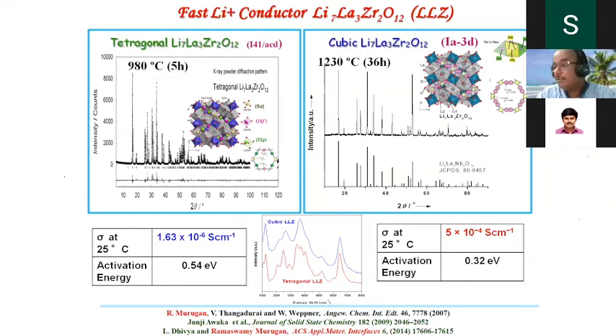God favored me. I used to prepare this material with alumina crucibles, not like other people, who used platinum and other things. When I put it for 36 hours in a particular furnace at 1230 degrees Celsius, aluminum from the alumina crucibles entered into my pellet and replaced some of the lithium, and then the aluminum sits over there.